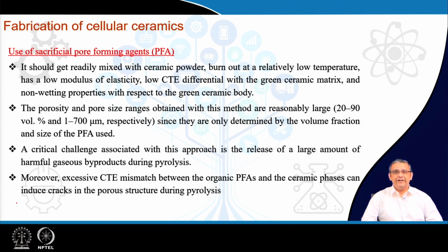This method is very attractive, as I already mentioned, and it can provide materials with a very wide range of porosity, from 20 volume percent to 90 volume percent, and also a wide range of pore size, from even 1 micron, so very fine pores, to even 700 microns or higher.